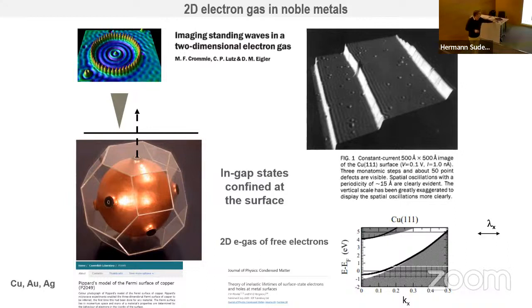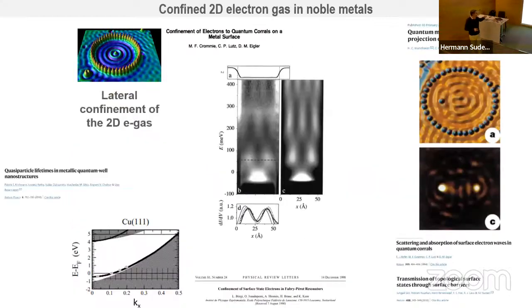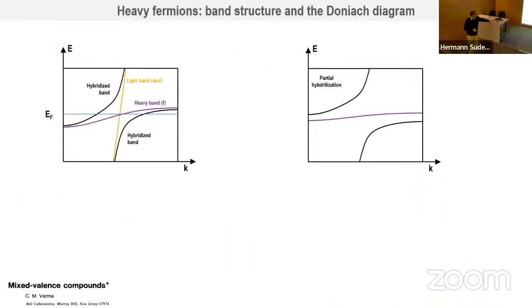So you can follow as a function of the energy, and you see that this wavelength changes because the K vector changes. So that's kind of nice. And of course, when you have this two-dimensional electron gas, you can put barriers. And when you put barriers, then you have an energy quantization. And the energy quantization goes to a few hundred milli electron volts here, and you can build these nice systems, which has been studied for a long time.